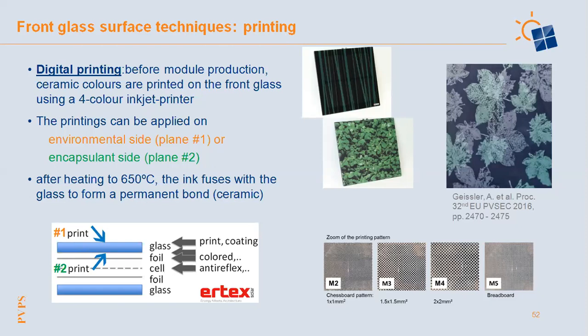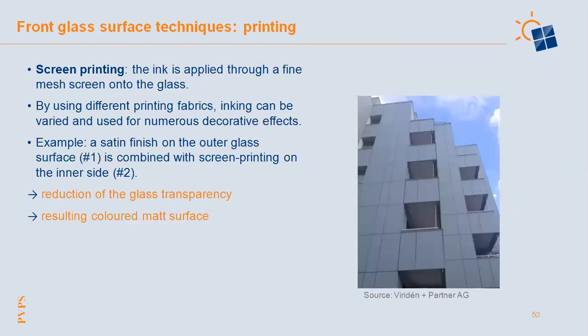And it's possible to print different patterns so that at least 50% of the glass is not printed, so that enough light can pass through the glass to reach the cell and produce electricity. Another type of printing is screen printing. Here the ink is applied through a fine mesh screen onto the glass, and you can use different fabrics as a mesh screen to generate different decorative effects.